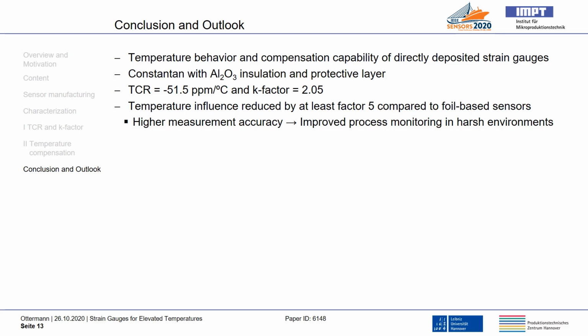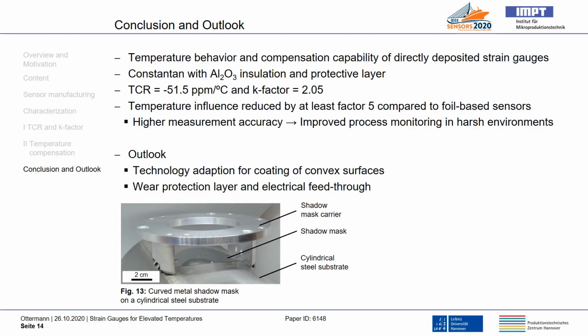With the directly deposited half-bridge strain gauges, a temperature influence reduction by at least factor 5 was possible compared to foil-based half-bridges. As we can see, we were able to reach a higher measurement accuracy, which can improve the process monitoring in harsh environments such as underground at bottom hole drilling tools. Let me tell you about the upcoming work.